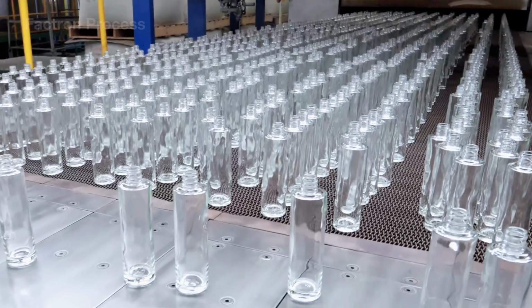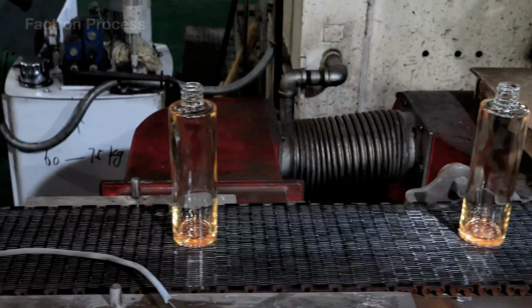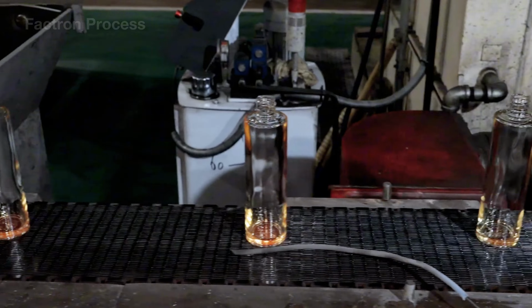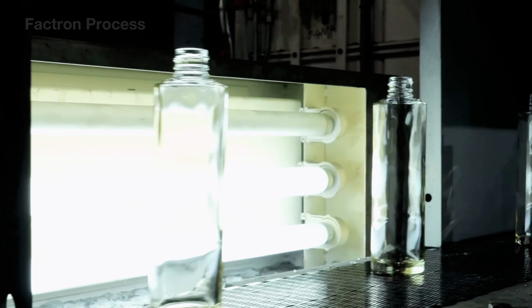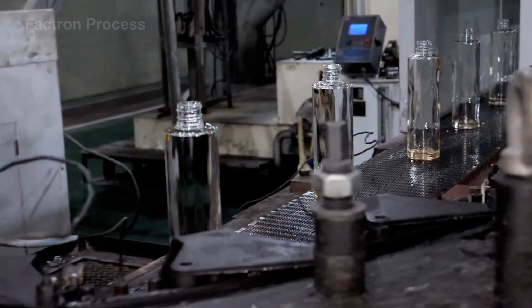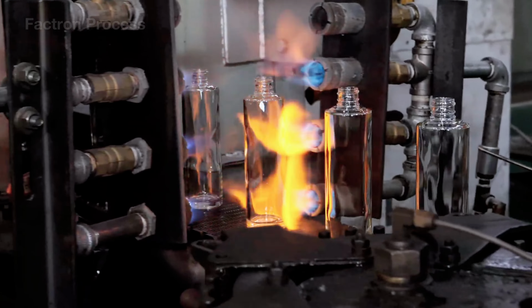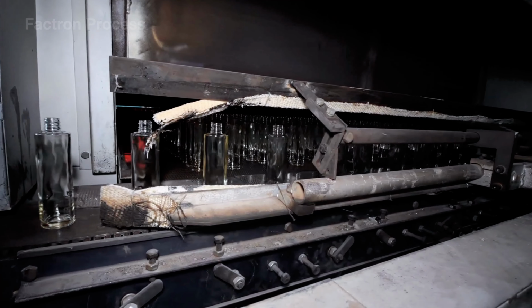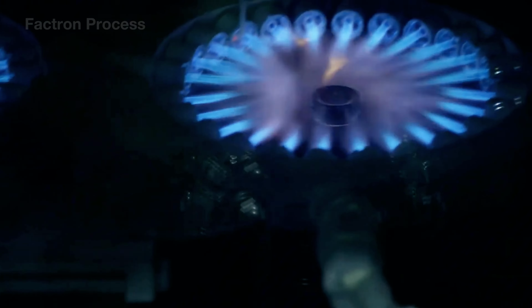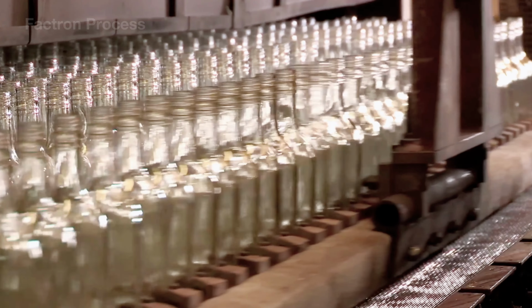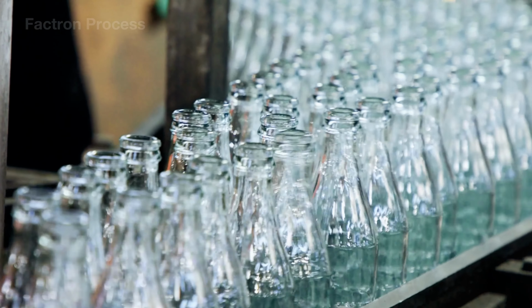New bottles are sent into the annealing lehr to cool down slowly. Why does this have to be done slowly? Because if glass cools too quickly, it will create internal stress. The outside may look perfect, but inside there are invisible points of tension. With only a light impact, a temperature change, or pressure during transportation, the bottle can crack or break.